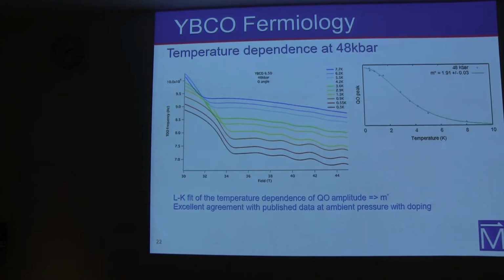So by taking the Fourier transform amplitude and plotting this amplitude as a function of temperature, we get this curve, which we fit with the Lifshitz-Kosevich equation. And this gives us the effective mass of the carriers. And we get about 1.9 electron masses.